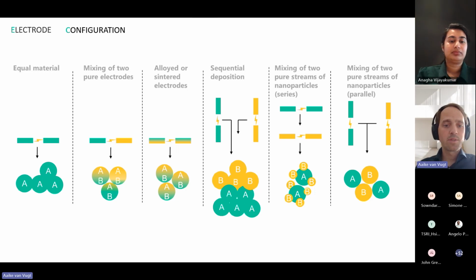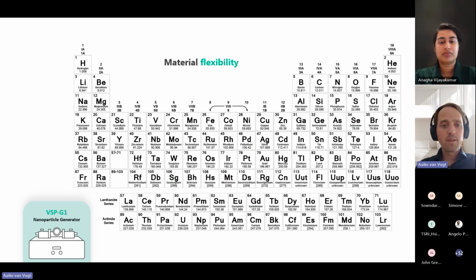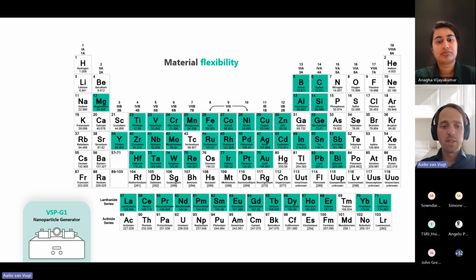And we know that in the sparking process, the particles will have very close to the original composition that you used. By using multiple sources, for example in the printer, you can use 2 of those nanoparticle sources. You can play around with all kinds of more complex structures that you can print. So there's a lot of flexibility already on that side. The other flexibility comes if you look into the materials that we can process. Again, we process the material using this very high temperature plasma. And because of that, almost all solid materials at room temperature will evaporate at that temperature. So all the elements in green can be processed with the same system. You can process them in pure form or any of those mixtures that I showed before.